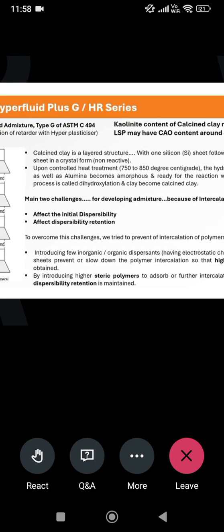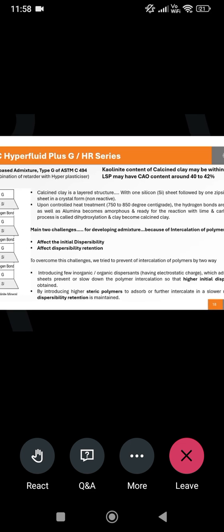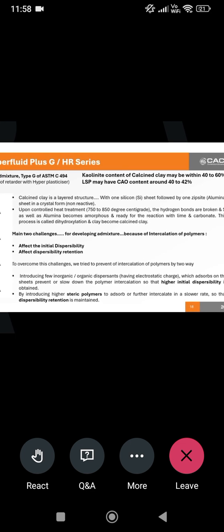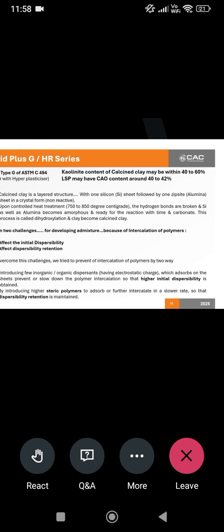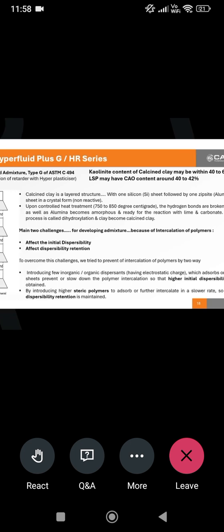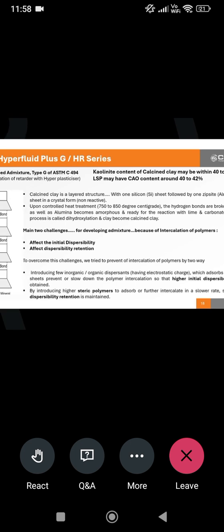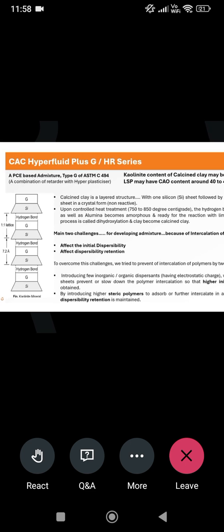What is the disadvantage for the admixture? When admixture is introduced, due to the extra foliation, the admixture goes into the sheets rather than dispersing the cement particles. So your admixture demand may be more for a given workability. This is the first disadvantage. All the admixture molecules are entering into the gaps of these sheets. The rest of the molecules will not be available for slump retention or further dispersion. That is why flow and slump retention are also low in this case.